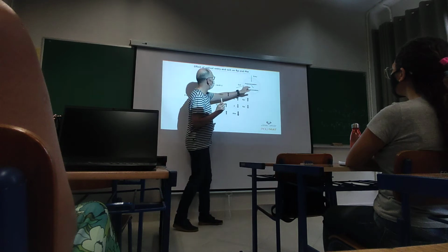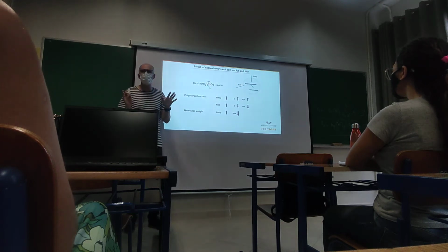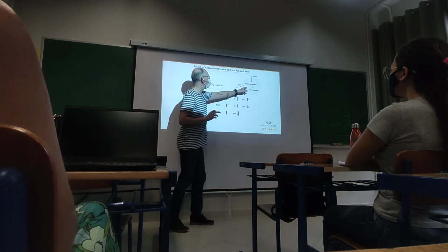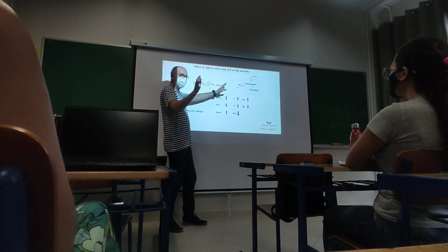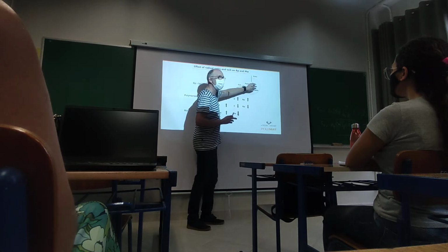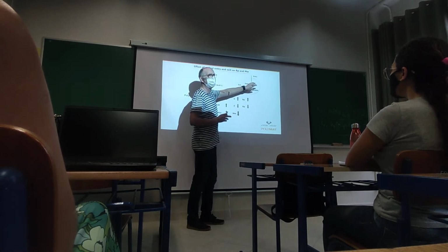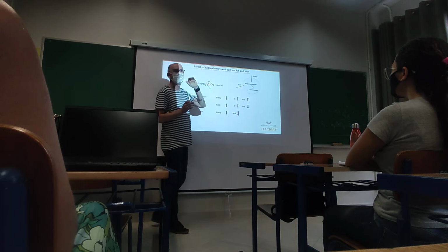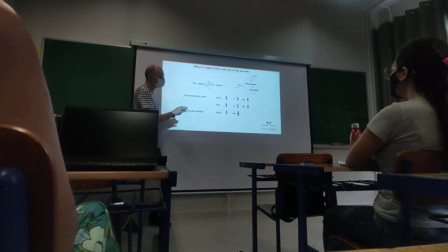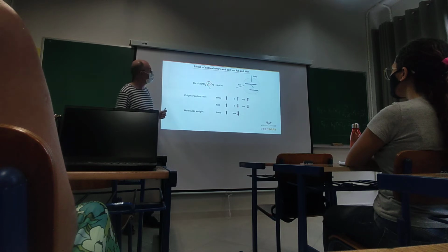If the rate of exit increases, it's not clear what will happen with the molar masses, because for the rate of exit to increase, as we will see now, we need to have transfer reactions in the polymer particles. And transfer reactions cut the molar masses.